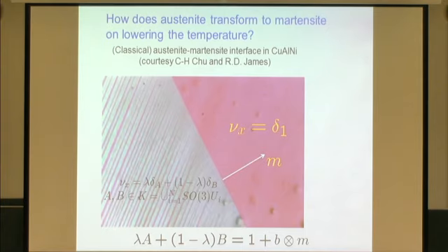And the normal to this habit plane here is given by saying that the weak limit here, the deformation gradient of the weak limit, has to be compatible with the weak limit over here, which is the identity, namely that the difference between those matrices is a matrix of rank 1, and then the second vector, little m, gives you the orientation of the normal.